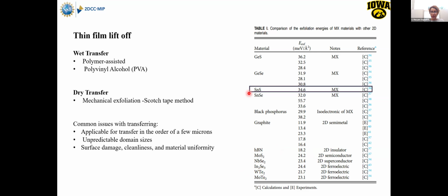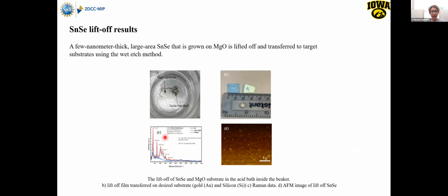So here we are interested in looking at the tin selenide, this one right there, and its exfoliation energy is about 32, so a lot higher compared to this one. That was part of my program I've done at Penn State. And here is the result we have. The substrate we grew was around 1 centimeter by 1 centimeter, and we could lift off the entire thin film without any tear, without any damage.